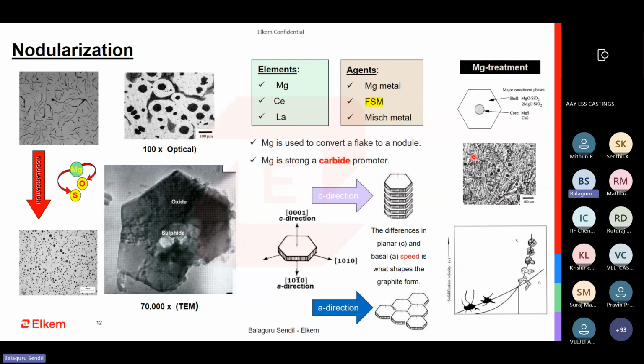So magnesium is a very strong carbide promoter, and it should be kept to the bare minimum possible. Keeping more magnesium is not advisable. It is going to cause a problem. With respect to carbides, when you have more carbides and poor nodule count, it is going to cause shrinkage. So the only advantage of magnesium is that it can convert a flake to a nodule.